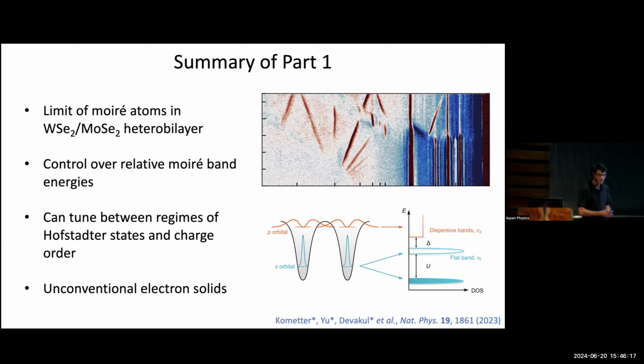There's something here about the compressible states in between the various phases, and what happens at lower temperature? So you're talking about the blue regions here, right? Yeah, and maybe like between things. Oh, like here or here. Sure, yeah. So those blue things, I'll tell more about them in the second half of the talk. These are indicative of phase transitions. As you go from this spin singlet to the spin triplet, you can see there's this sharp blue feature. This is associated with a phase transition between two distinct electronic states. And similarly here, if you go to lower temperature, these sharpen up and you can see that they're associated with switching from this kind of Hofstadter regime to this funky charge order.